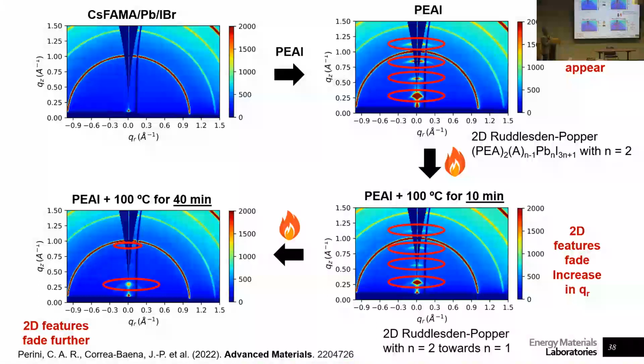And for us, it's an organic material, and the organic materials, you can imagine, are not as resistant to high temperatures as aluminum oxide. So these organics, we're trying to tailor them to have different functionalities, maybe to cross-link so that they don't move. But here, this was our first indication that this organic is moving, and so we want to make sure that we design those organic molecules so that they don't move, so that they don't show a very high degree of crystallinity, and then over time kind of fade away, right? So yeah, those are organic materials.